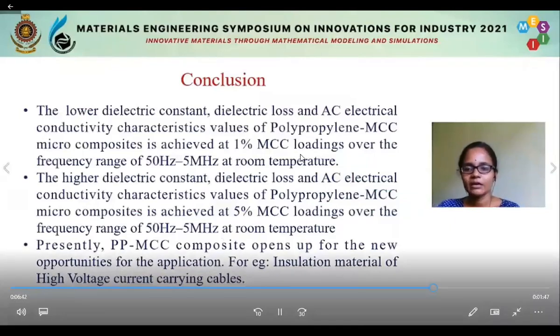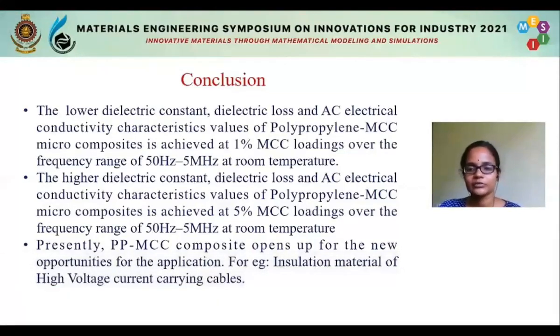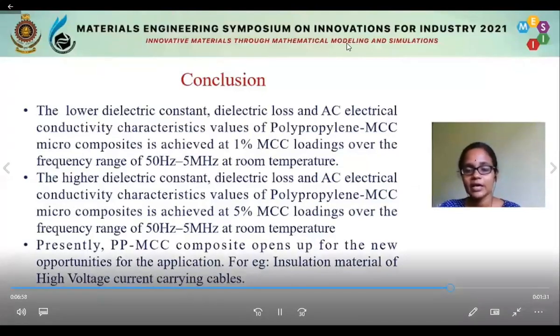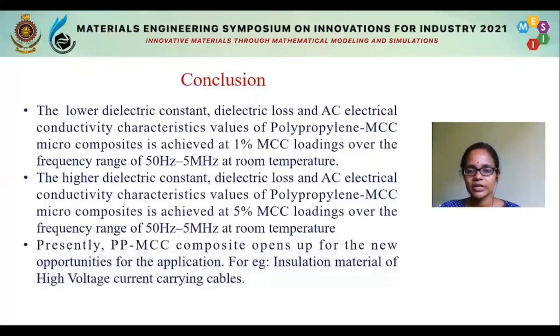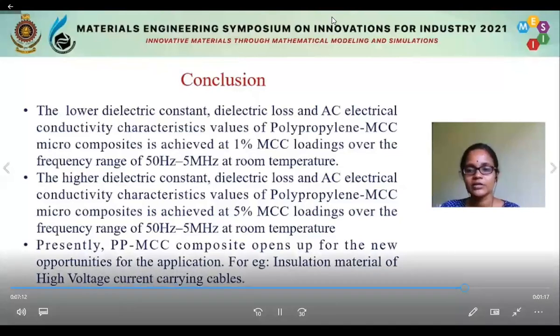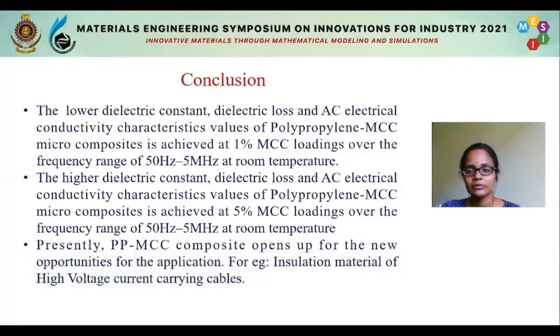The results that we gained are that lower dielectric constant and dielectric loss were achieved by the polypropylene composite with 1% microcellulose composition in the frequency range of 50 Hz to 5 MHz at room temperature, and higher values of dielectric constant and dielectric loss were obtained by the composite with 5% microcellulose composition in the frequency range of 50 Hz to 5 MHz at room temperature. So, MCC-based polypropylene composite opens up new opportunities in applications such as insulation material for HVDC cable.